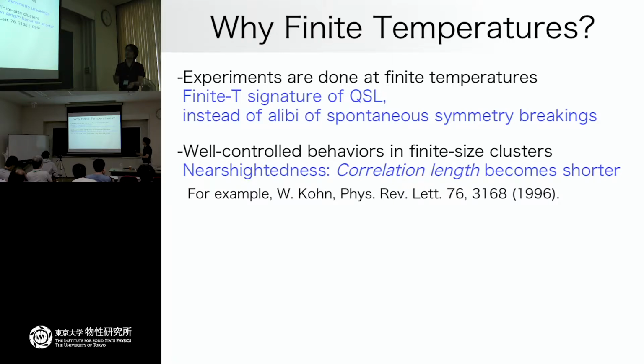we want to find some finite temperature signature of the quantum spin liquid instead of the signature of spontaneous symmetry breaking. But in addition to that, if you look at finite temperature, we can have a bonus, because even if you calculate a finite size cluster, the finite temperature gives us a well-controlled behavior, thanks to the nearsightedness of the correlated system. Because at finite temperature, correlation lengths become shorter than in the ground state.